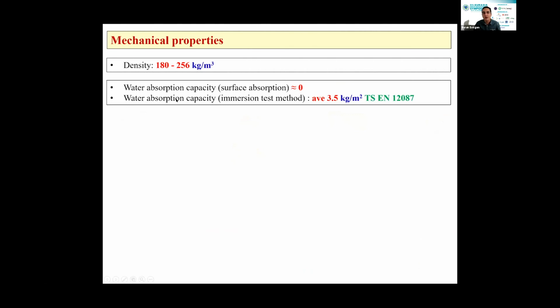And let's talk about the mechanical properties of our foam glass materials. And these 6 different foam glass materials, final products, have superior mechanical properties, and their density changes between 180 to 256 kilogram per cubic meter. And this density range can be reached up to 400 kilogram per cubic meter around worldwide. And water absorption capacity in terms of surface absorption is around 0. And it can also be used as waterproofing at the surfaces.